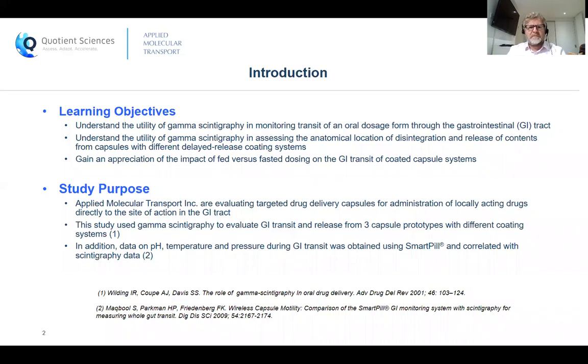coated capsule system. The rationale for the study is that Applied Molecular Transport are evaluating targeted drug delivery capsule systems to administer drugs with local activities to specific sites in the GI tract. Gamma scintigraphy was used to evaluate GI transit and release from 3 different coated capsule prototypes. In addition, pH, temperature, and pressure data were measured from a co-administered smart pill with particular capsule doses.